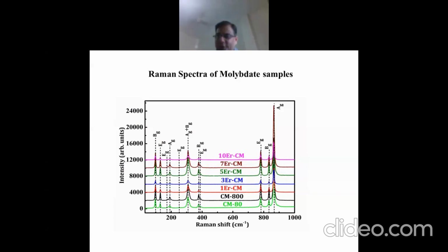There was a question from the audience: what is the power used during these Raman measurements? These Raman spectra were measured at an excitation wavelength of 514.5 nanometers generated by an argon ion laser. The maximum power of our laser is about 25 milliwatts, but when we actually do the measurements, we use a power level of about 10% of this laser power. That means 2.5 milliwatt is the maximum power that may be incident on the sample. So the laser power used during Raman measurements is 1 or 2 milliwatts, while the maximum power of the argon ion laser we have is 25 milliwatts.